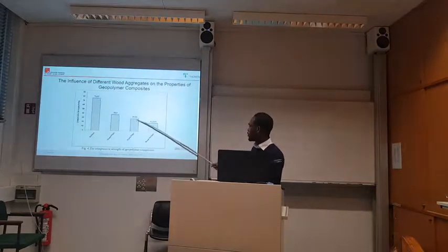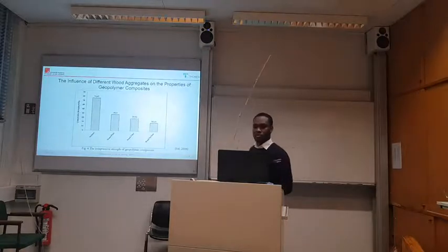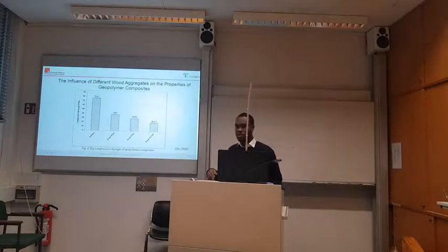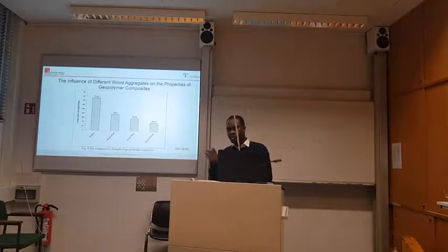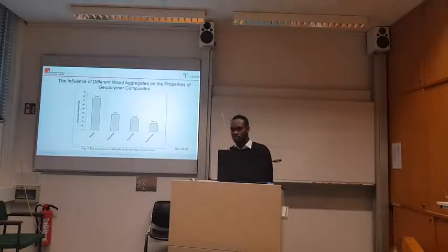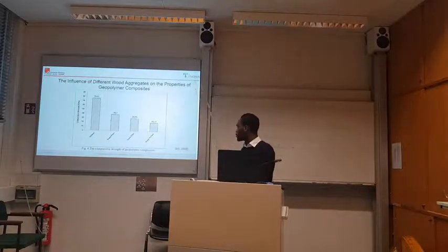Here we have wood that is a fiber, and mixing fibers, like I told you, is mostly not easy, especially on the laboratory scale. If you mix fibers, sometimes they form these balls and other things. The dispersion of these fibers is not so easy with a laboratory mixer as compared to the industrial scale. They have better mixers, but in the laboratory we have a different kind of mixer. So the mixing is also a problem.